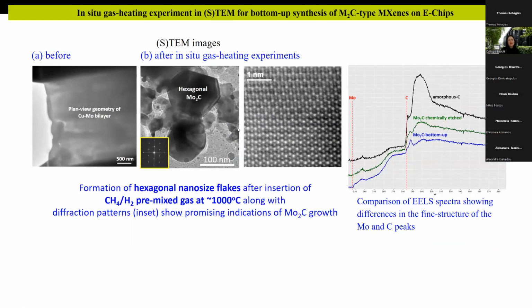So here is a summary of what happens before and after the in-situ gas heating experiment. You can see that we have the formation of nice hexagonal nano-sized flakes, and also with high-resolution imaging and with EELS spectroscopy, we verified the structure of molybdenum-2 carbide. So the first challenging part was successful.